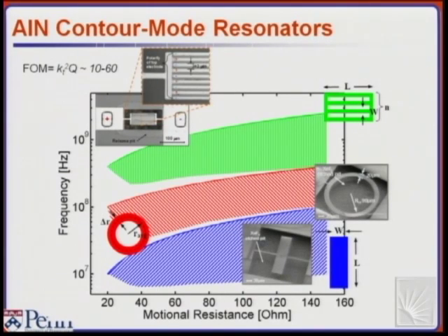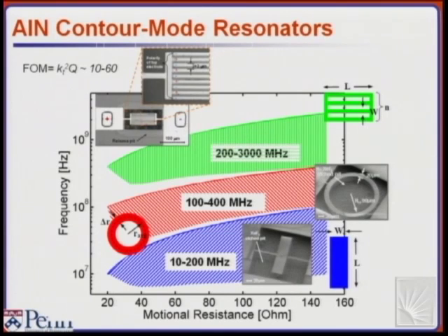We use rectangular bars, where you have a single element of a finger, like a single finger. We can even wrap that finger around and make it into a ring, which is a geometry that we almost abandon now. Despite making for good SEM pictures, that big hole is actually a waste of space. So it's not so interesting anymore if you want to compact and squeeze many devices in a small area. Whereas this is a much more compact solution, and we can go from 10 megahertz to 200 with this structure, 100 to 400, and we've seen 200 to 3 gigahertz with this type of structure.